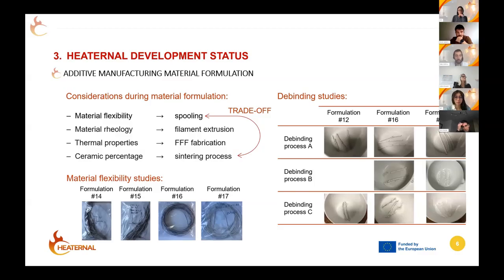On the other hand, regarding the advances in the material formulation itself, it's also quite challenging because of the different aspects that need to be taken into account. Amongst them, there's the material flexibility that you need for the spooling process after the filament extrusion. The material rheology has to be right for the filament to have an optimal extrusion. Then the thermal properties need to fall into the suitable temperatures for fused filament fabrication. And finally, the ceramic percentage needs to be as high as possible in order to ensure the maximum density is achieved after the sintering process.